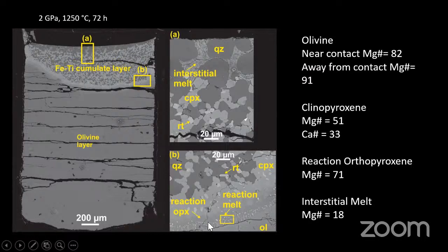If you zoom into this part, it is the reaction melt, and this lies within a reaction orthopyroxene layer, and that is overlain by the FeTi cumulate layer, which comprises clinopyroxene, rutile, and in some cases ilmenite and quartz. When partial melting occurs, the melt mostly accumulates near the top of the FeTi cumulate layer. The olivine doesn't melt much, but this layer melts much faster because it crystallizes later, so it has a much lower melting point than the olivine layer. So it will melt first.